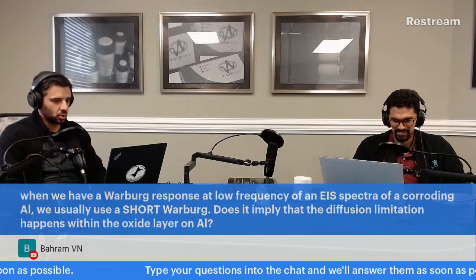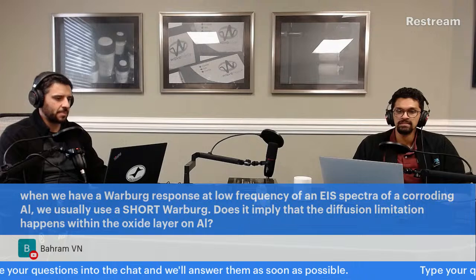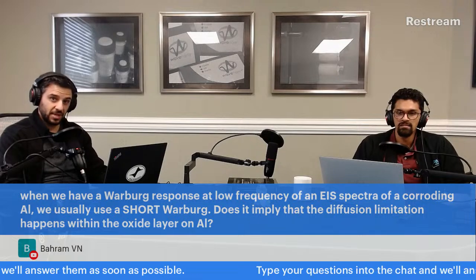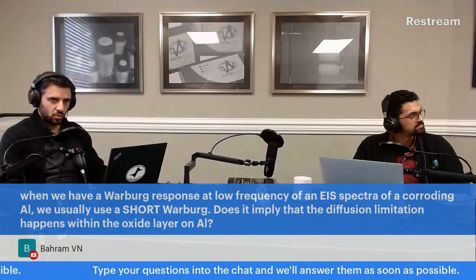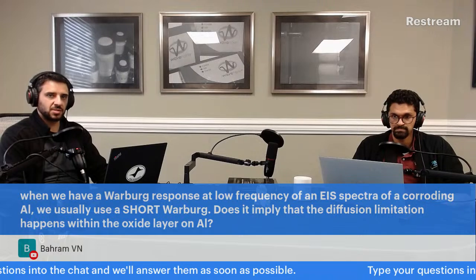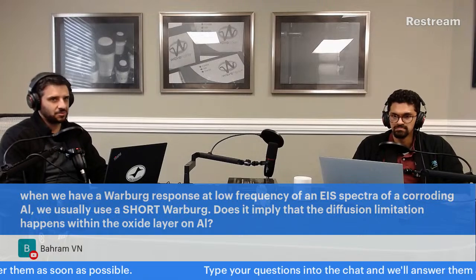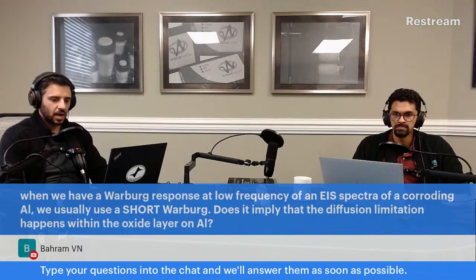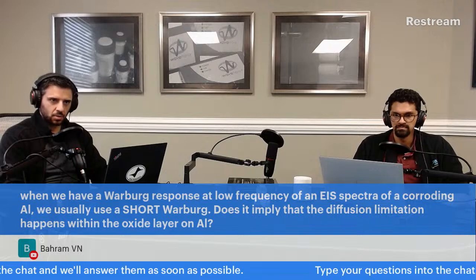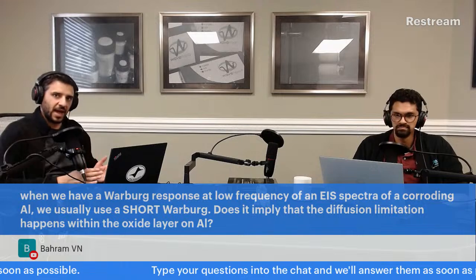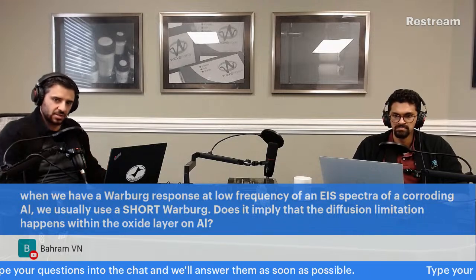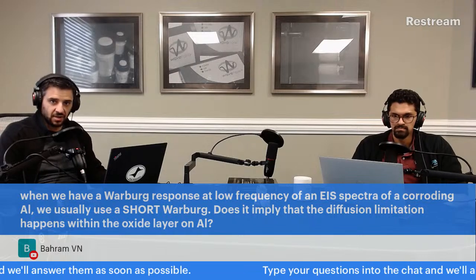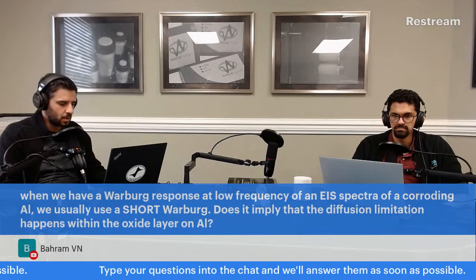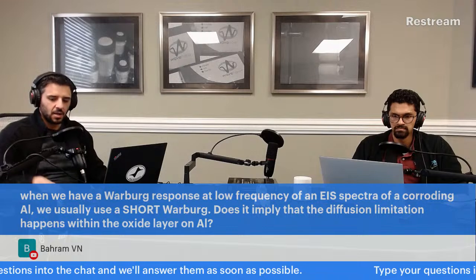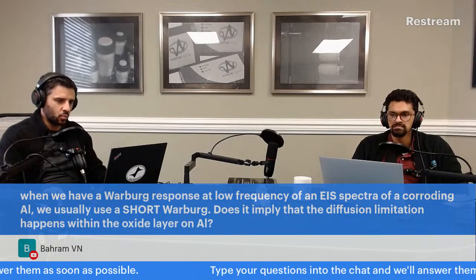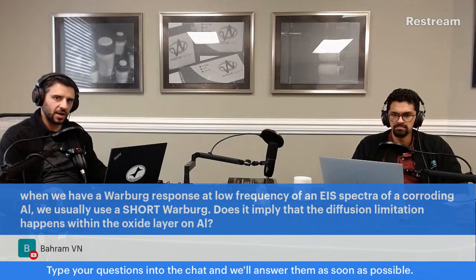We usually use a short Warburg, right? Does that imply the diffusion limitation happens within the oxide layer on the aluminum? Probably. Or at most a very small, I mean probably tens to hundreds of microns small, not much bigger than that. Like the diffusion layer we just talked about, right at the edge of the surface that does not extend any deeper into the solution, right? Because otherwise you would have an infinite Warburg, and the EIS spectra would reflect that.